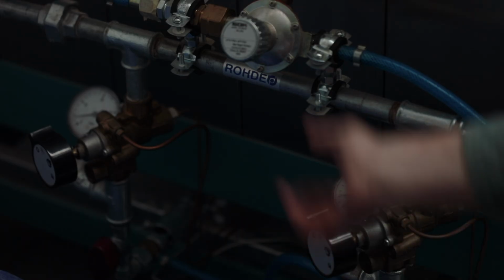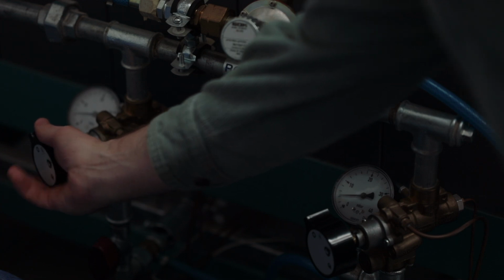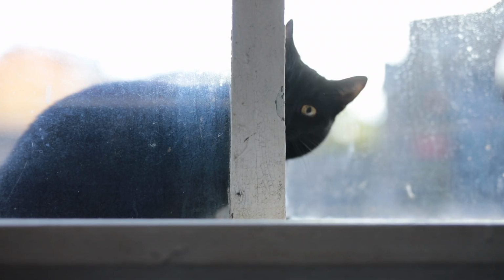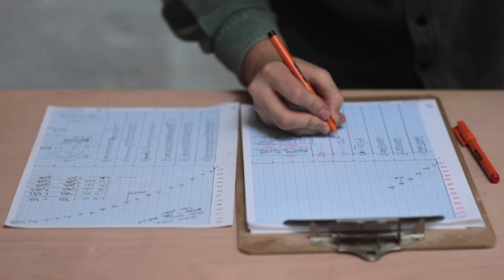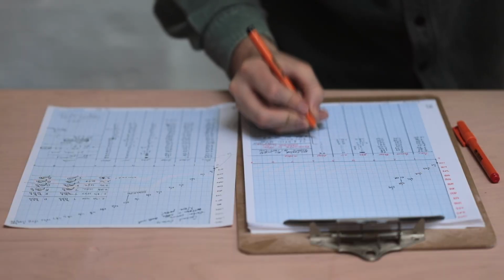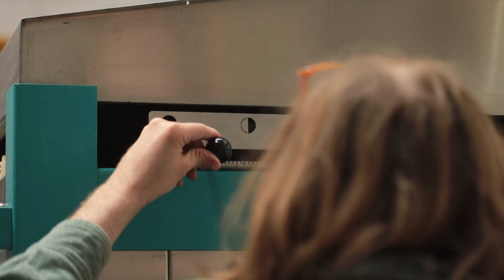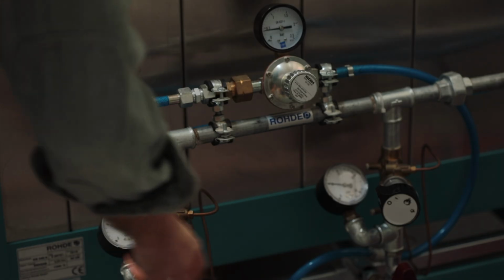For the first few hours I go very slowly, and then from about 300 to 800 degrees I can push it a bit more, which I do by increasing the gas pressure and the air pressure, and any change I make is recorded in my kiln notes. At 860 degrees exactly, the reduction atmosphere is started.